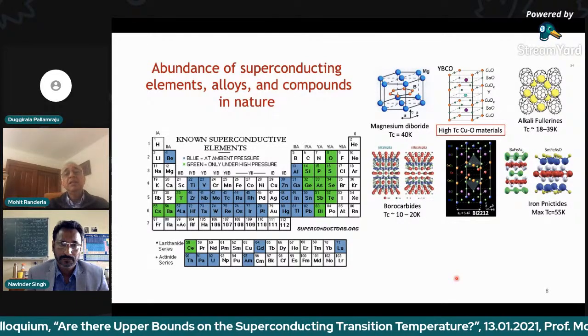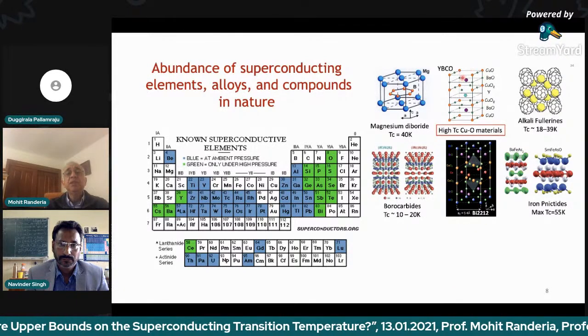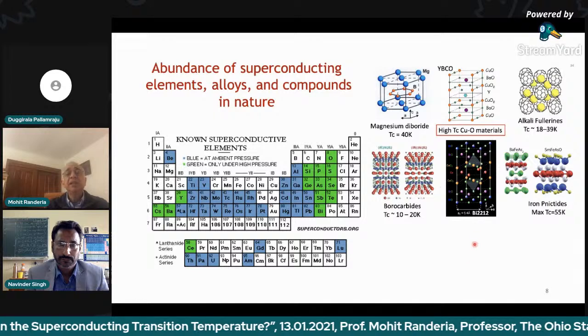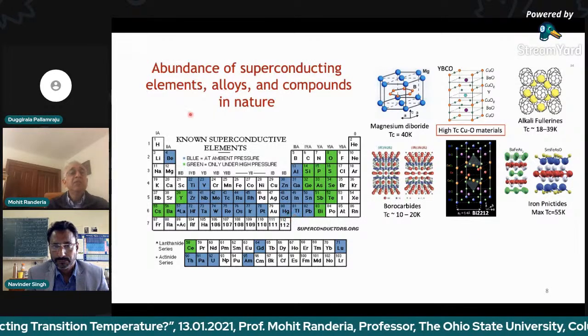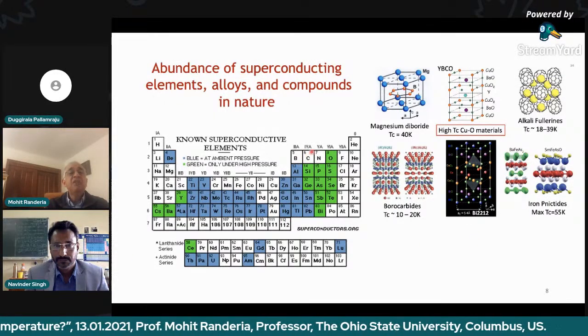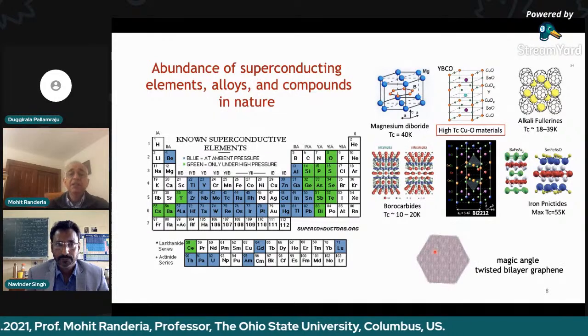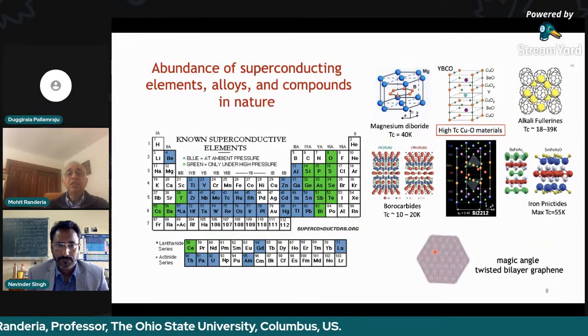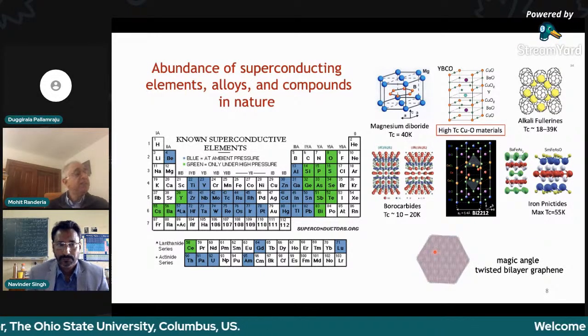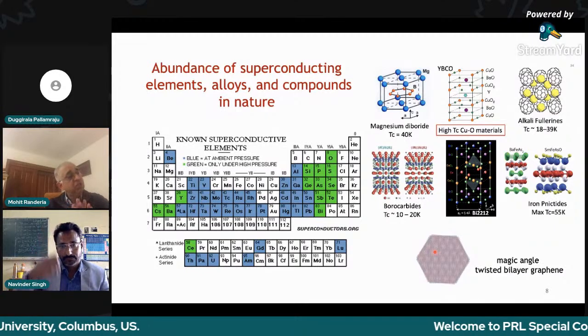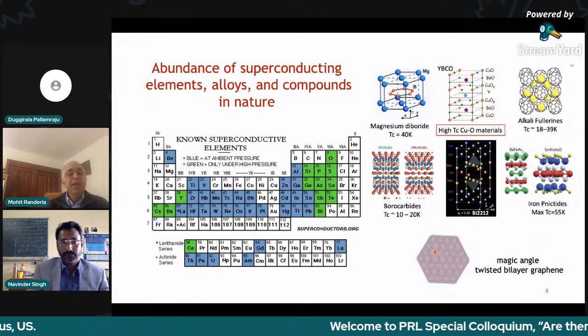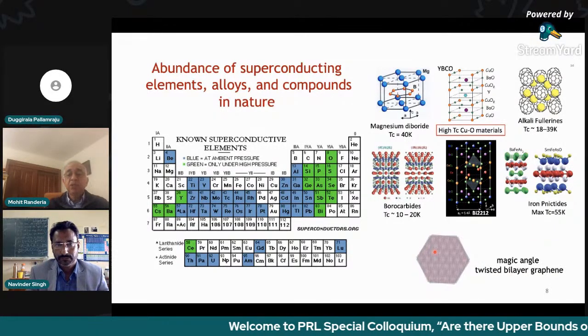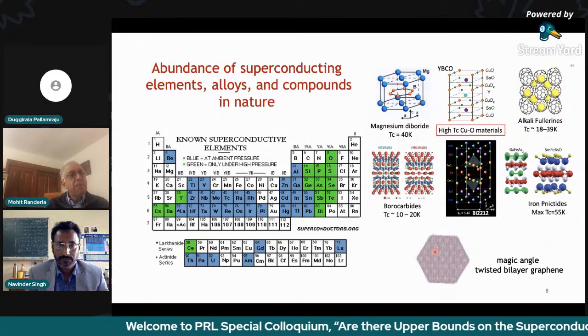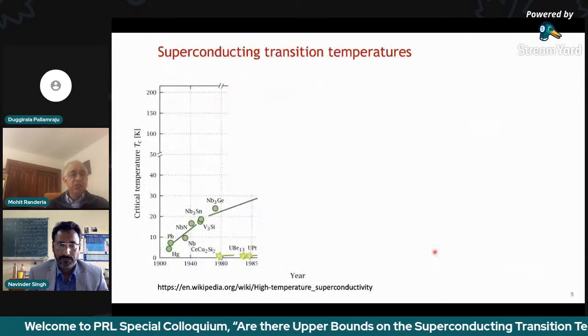Okay, and the high temperature superconductors, the cuprate materials, are shown in the middle, which are all superconducting. Now, this is an old periodic table where carbon was shown to be non-superconducting, but recently it has been shown that if you take two layers of graphene and twist them relative to each other close to a certain magic angle, that too becomes superconducting. So there's an abundance of superconductivity in nature.